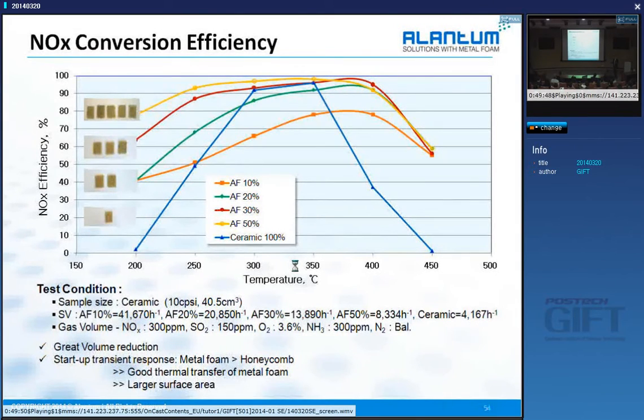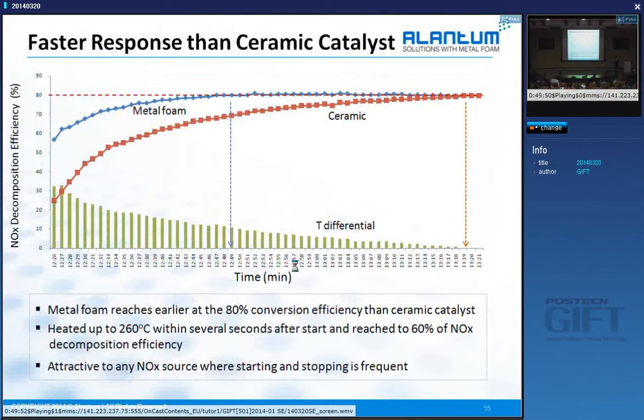This one shows in the next slide. So ceramic reaches about 80%, I don't know, this is 13 minutes, right? But our foam reaches 80% much faster. That's what we are talking about. Also it shows that they are heated up to 260 degrees within several seconds.